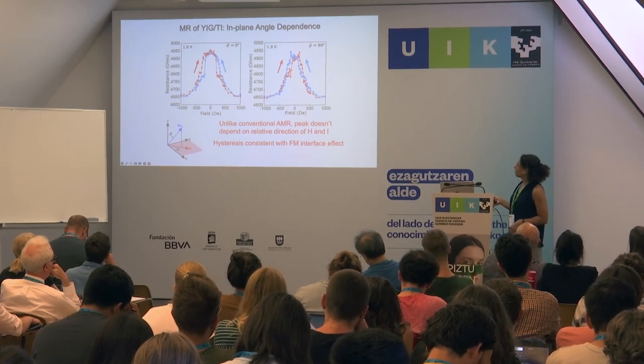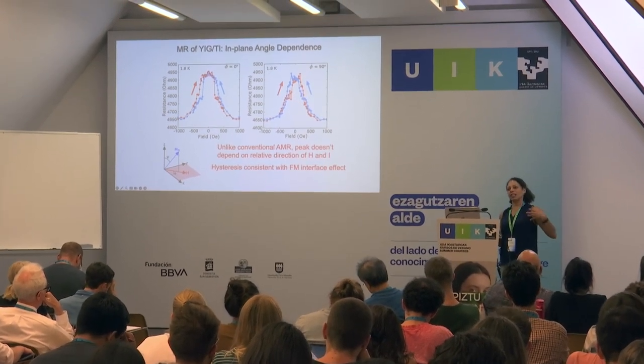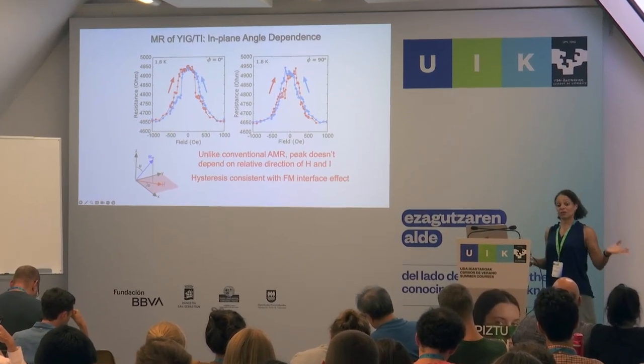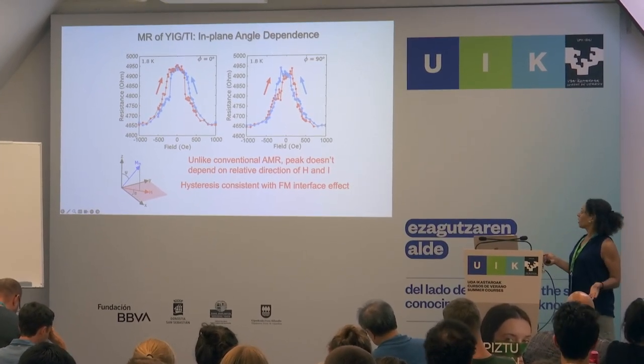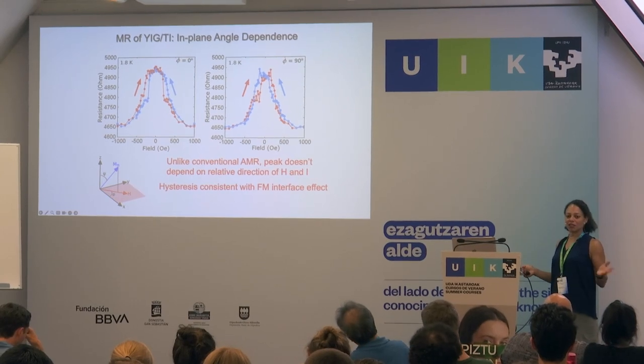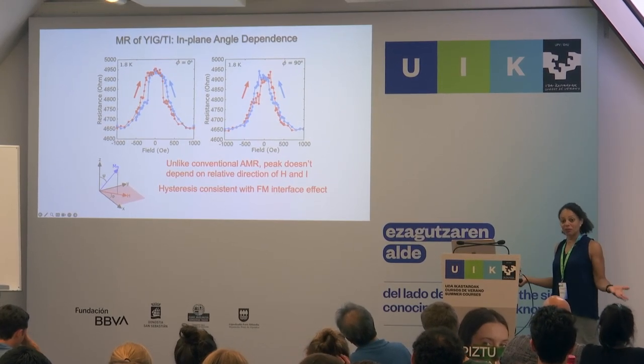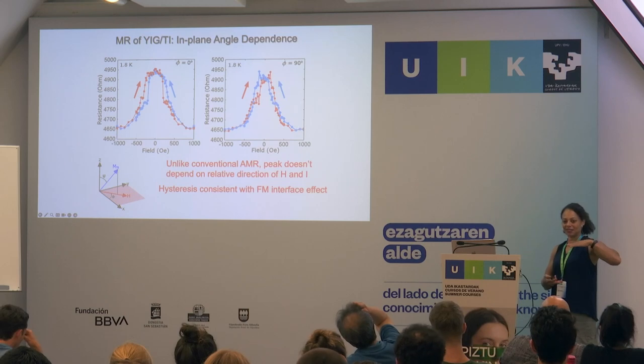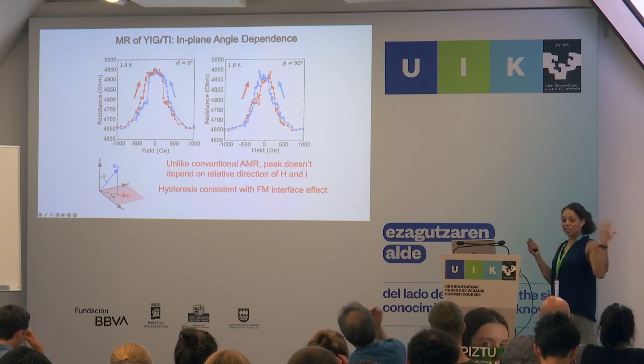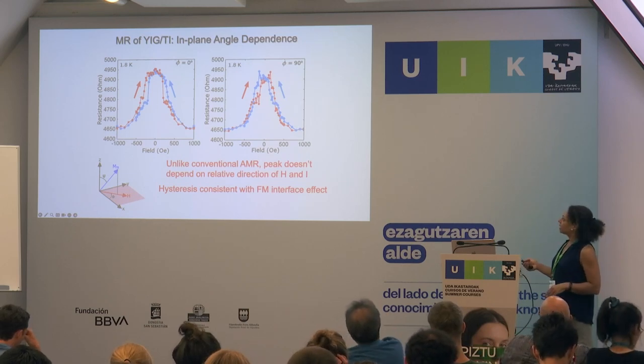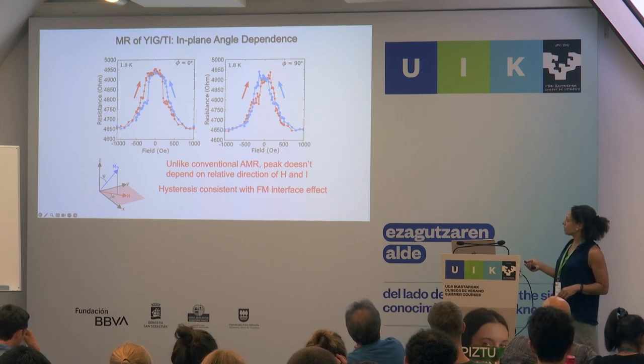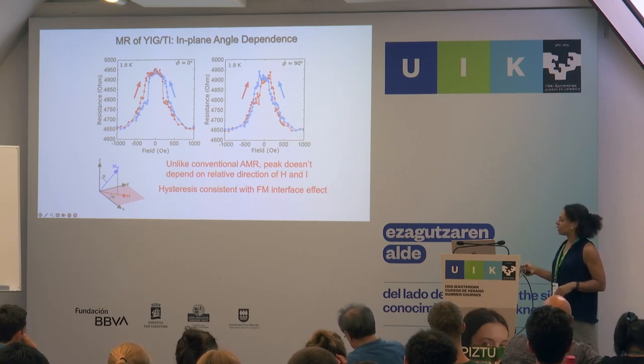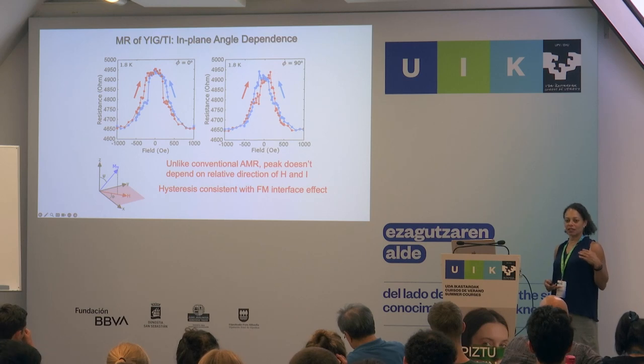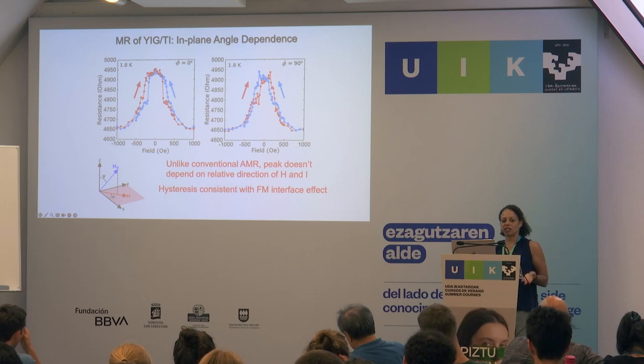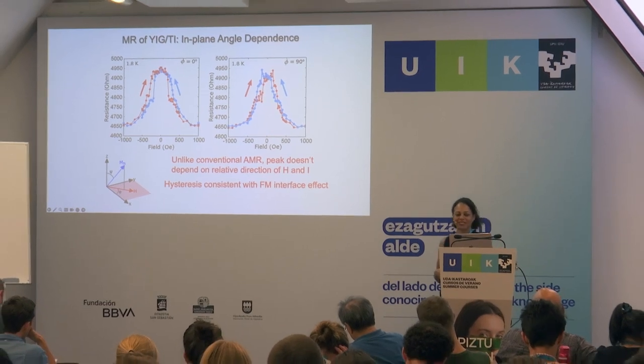And what I'll show is that we do believe that we're switching. So the point here is the YIG is doing the switching, but it's doing the switching in a much higher field than would happen with the YIG alone, which implies that you are getting some sort of coupling between the YIG and the bismuth selenide, right? Which is the first order, at least to see that sort of coupling. And then the magnitude of the effect and the temperature scale of the effect tells you that it's likely a surface state effect in the bismuth selenide itself. So that combination tells you that there's likely some sort of surface state switching in this case.